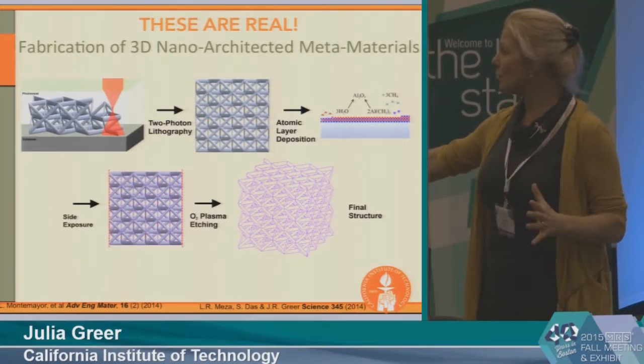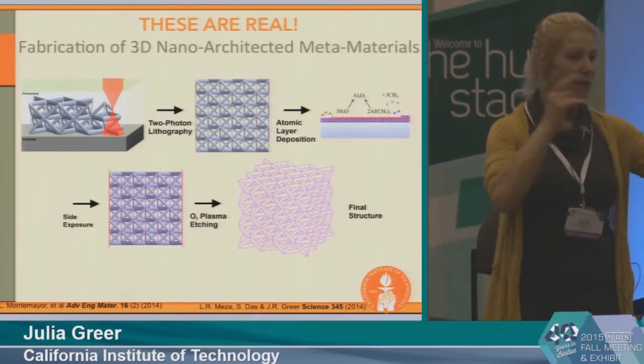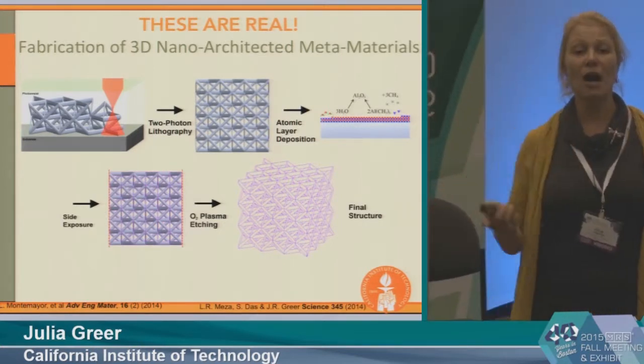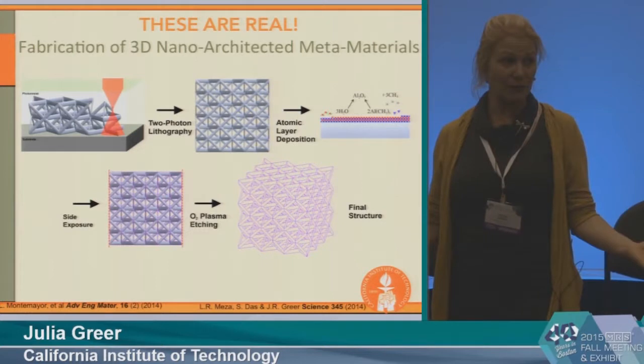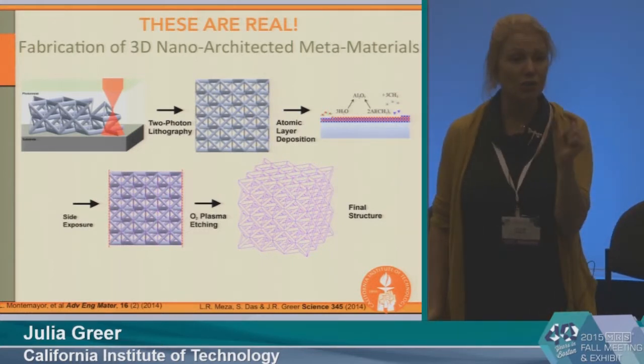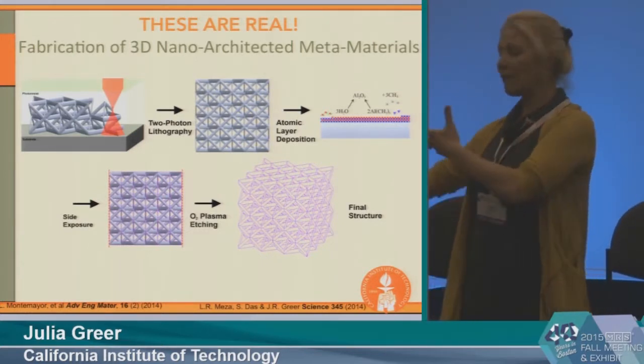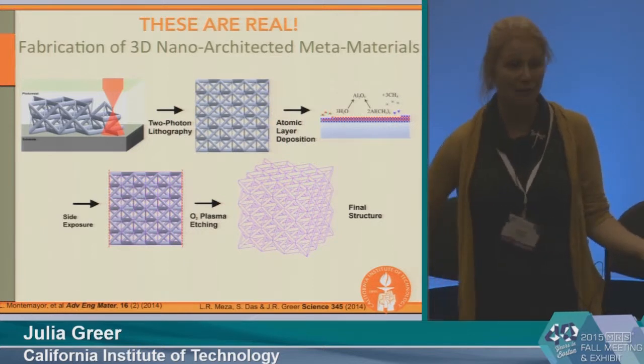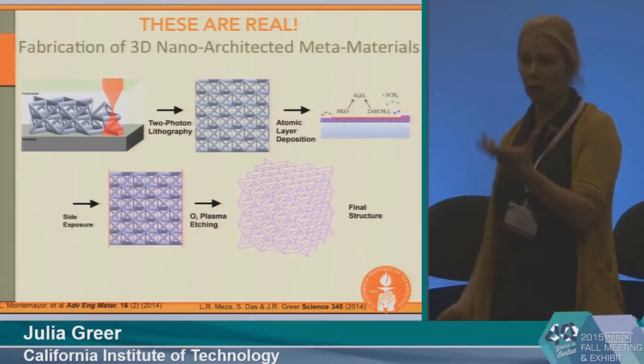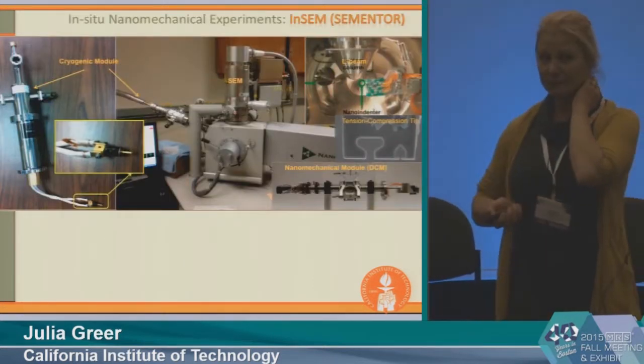And this is what shows you why we end up with something that's hollow, that's comprised of an interwoven network of hollow tubes that's made out entirely of the material that you deposited, and the largest dimension of the solid here is whatever the wall thickness is, so it's less than 100 nanometers. So we're fully in the regime where you were expecting to see size effects.